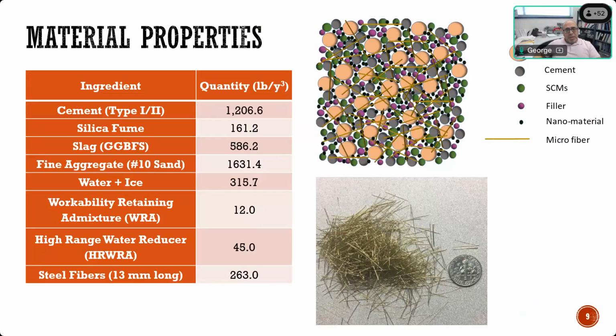In addition to that, of course, you have water and admixtures, and the amount of water is very small compared to the amount of cementitious material. The ratio is less than 0.2, which is a very low water cement ratio. However, with the use of high range water reducers and workability retaining admixtures, this allows the material to be very flowable and maintain its flow for a significant amount of time.